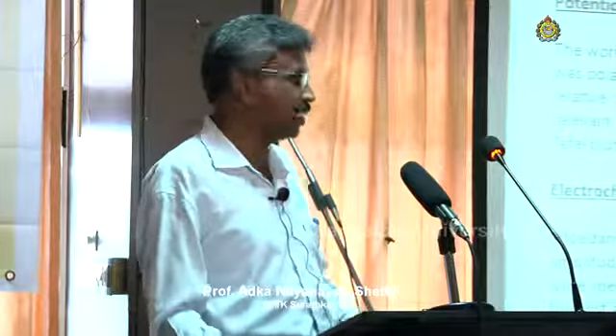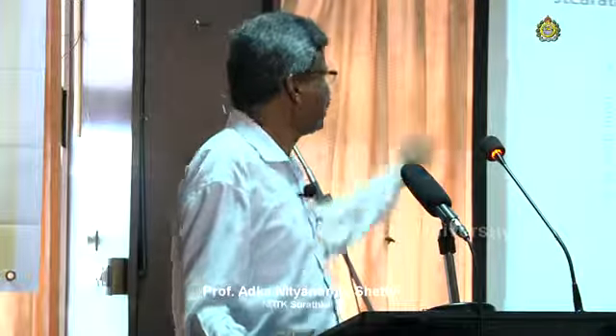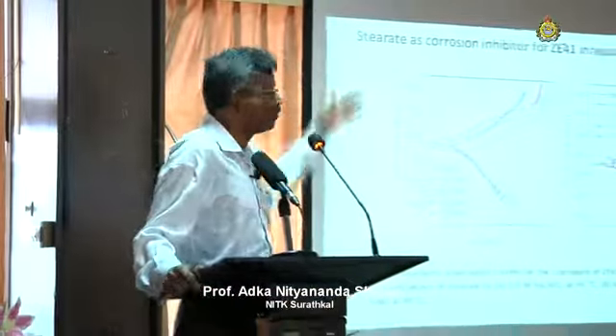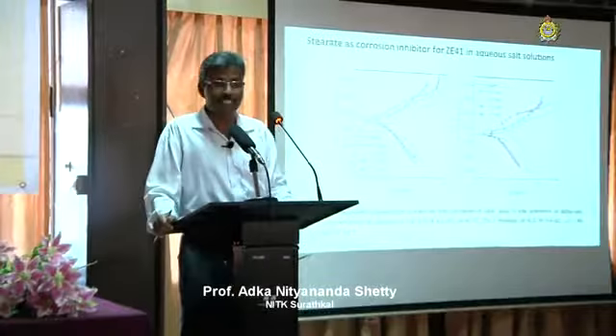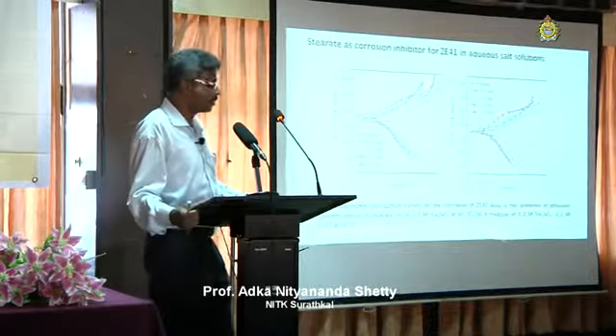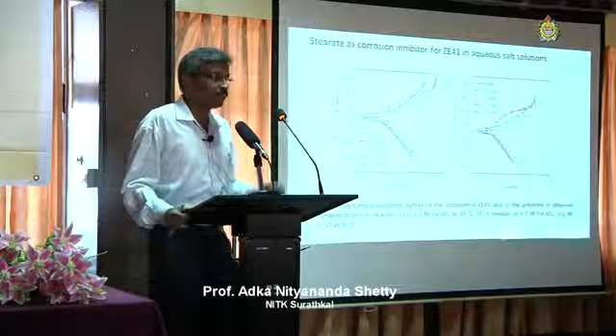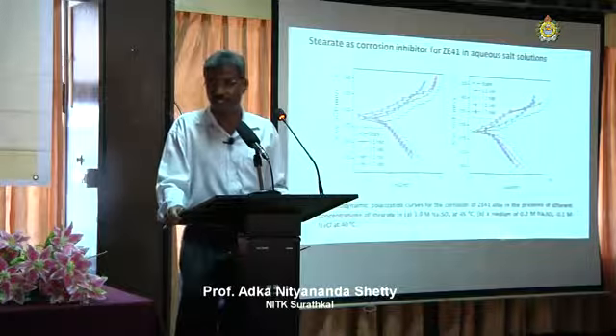Okay, I just tried to give some procedures. Next. This is the typical Tafel plot, or potentiodynamic polarization curves, for the corrosion of one of our samples, that is ZE41 magnesium alloy, in the presence of different concentrations of inhibitors.